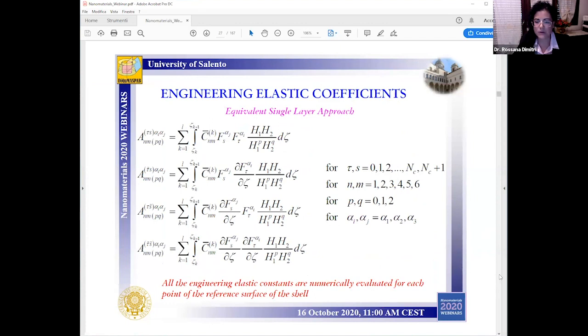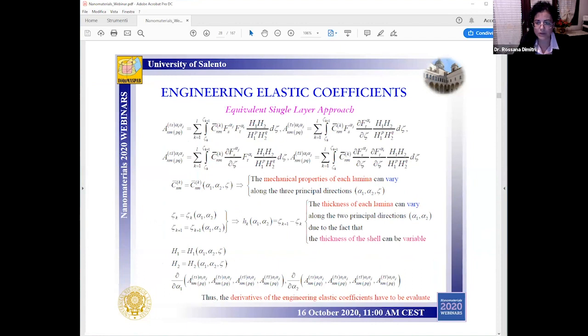And I want now to highlight an important aspect of this approach. I mean, the mechanical properties of each lamina can vary along the three principal directions. So we have this kind of coefficients, and we can consider that the thickness of each lamina can vary along the two principal directions, so the thickness of the shell can be variable. But to consider this kind of variation in this model, we have to evaluate the derivatives of the engineering elastic constants in a numerical sense. So I need a numerical technique to do this kind of mathematical operation.